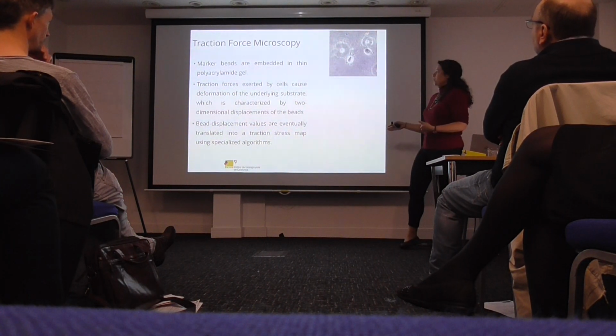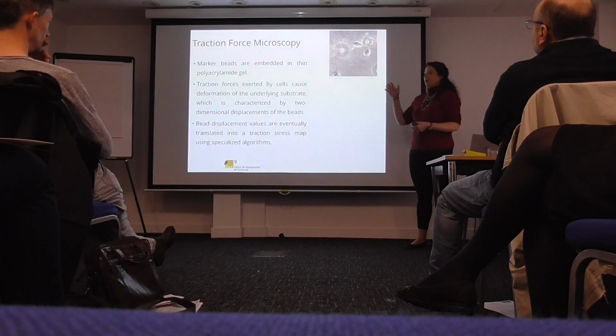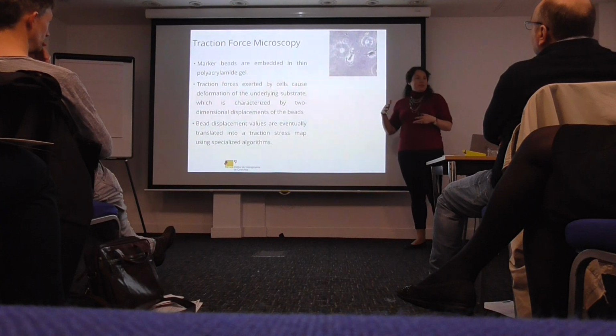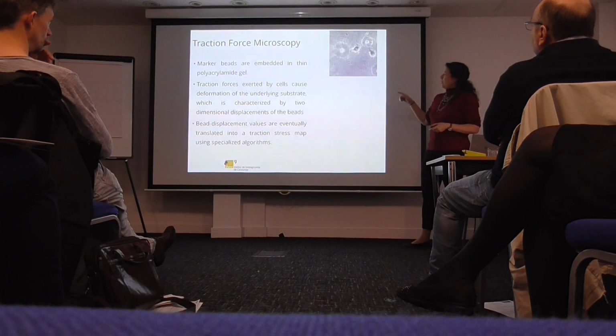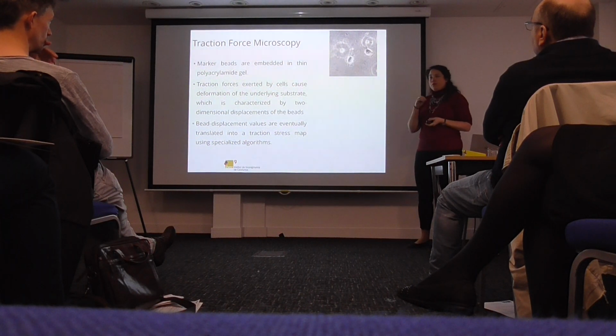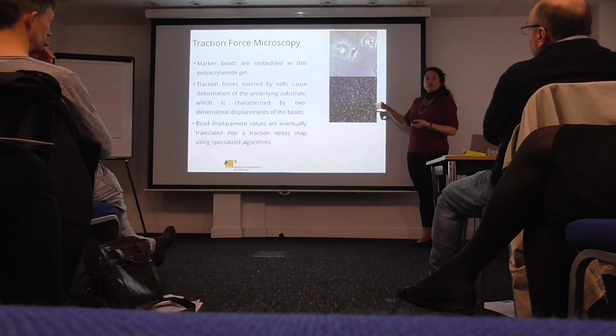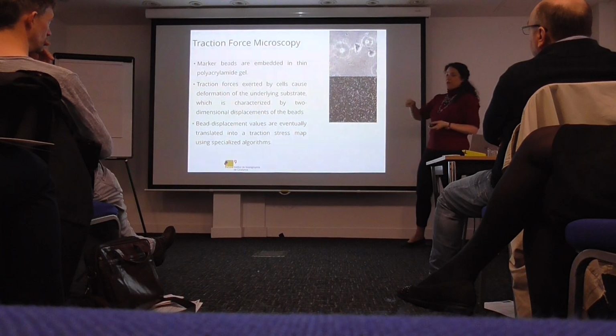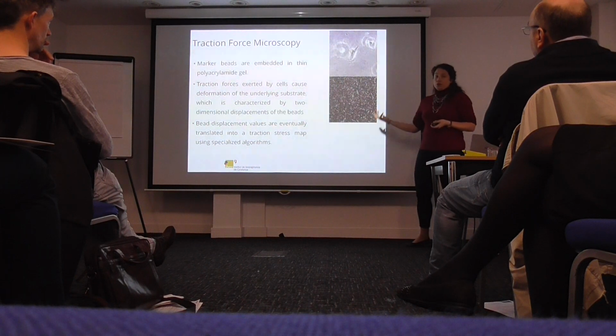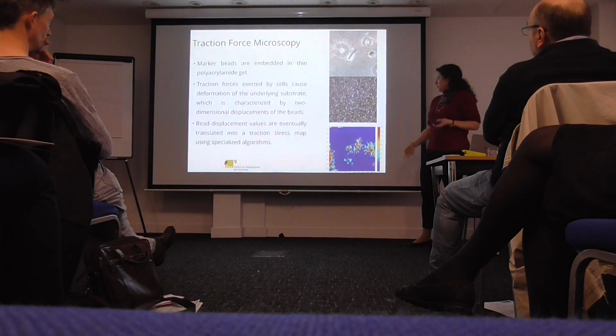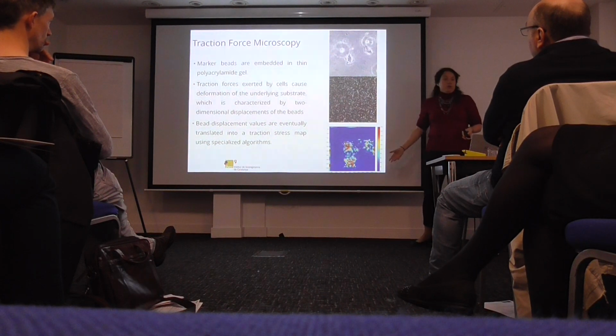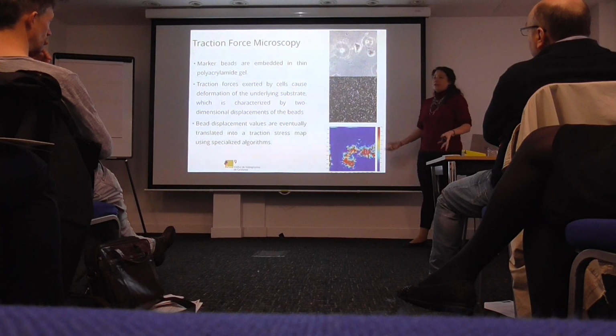So for those who are not familiar with it, in traction force microscopy you put cells on top of flexible gels. You were talking about polyacrylamide this morning. The reason why we really like polyacrylamide in this context is that if you put fluorescent beads inside of your polyacrylamide, you can measure the displacement of the beads at the same time that you're looking at the movement of the cells. Because it's a linear system, you know how much force the cell had to exert to move that particle. So if you've got the displacement and the mechanical properties of the gel, you know how much force the cell has exerted, and you can create force maps, which allow you to look at how much force a cell is generating at any point in time.